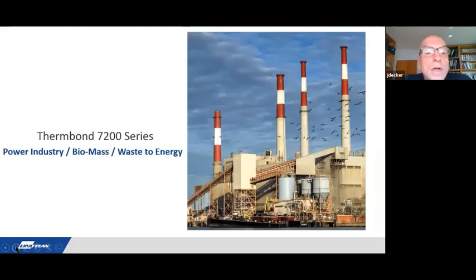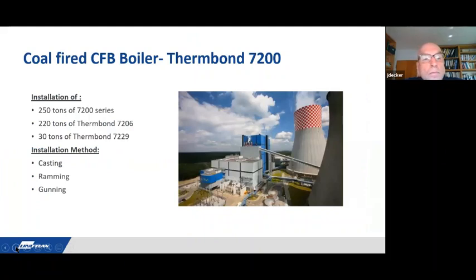Thermbond 7200 in the power industry, coal-fired power plants, biomass, waste to energy. That was our target industry to begin with. Coal-fired CFB boiler, one of our larger installations. We installed 250 tons in this furnace, and we used all methods: casting, ramming, gunning. No, we did not use pumping and shotcrete, but we used casting, ramming, gunning. And that's the advantage of this material.